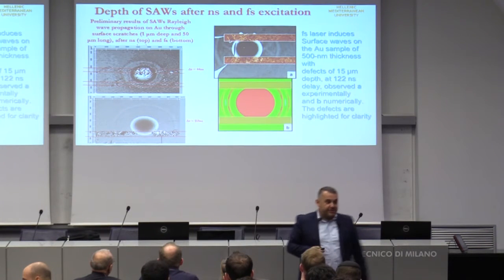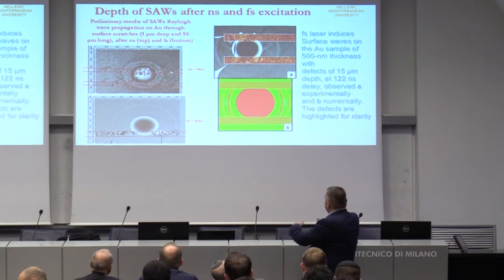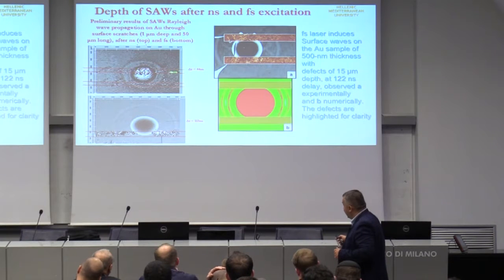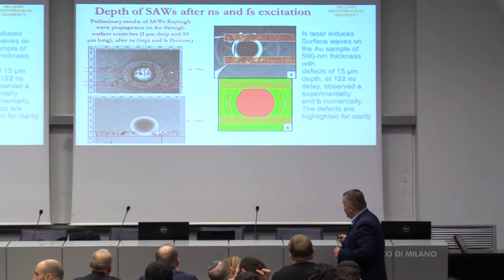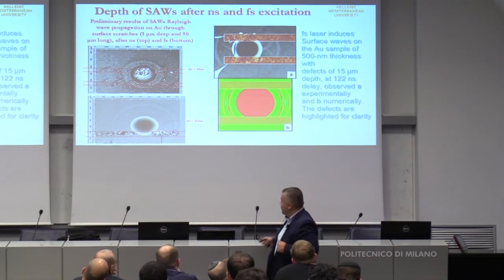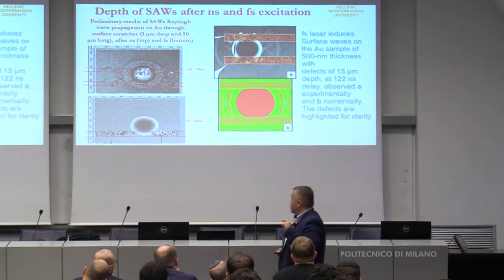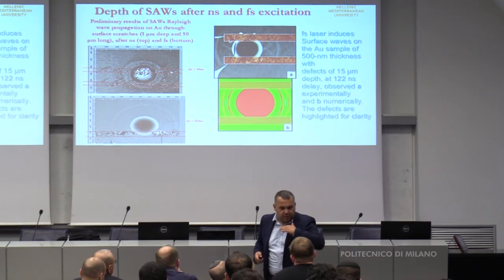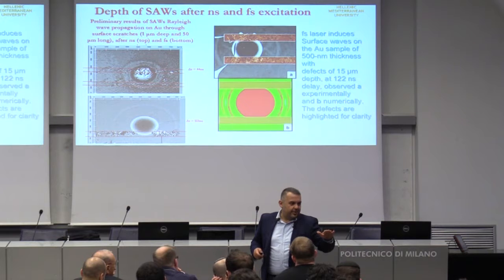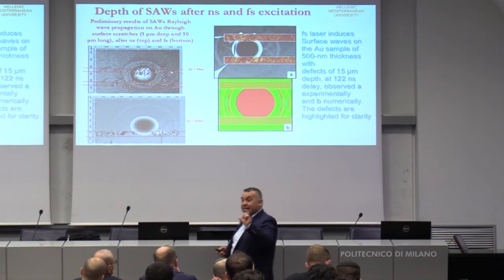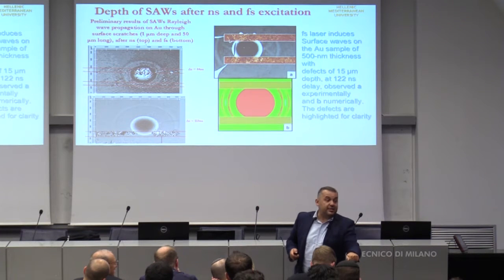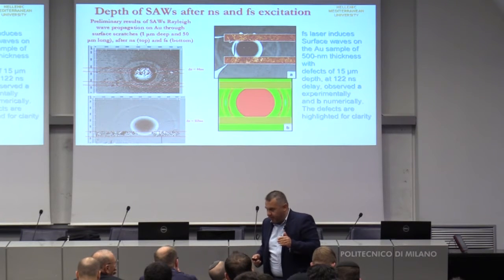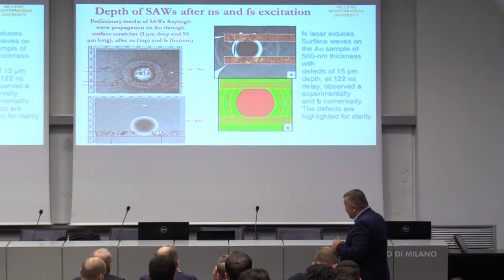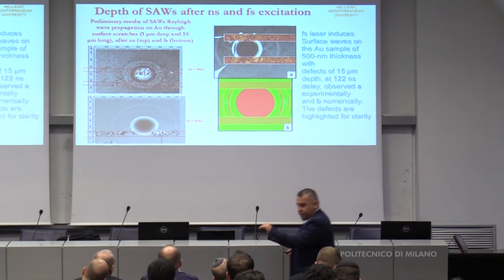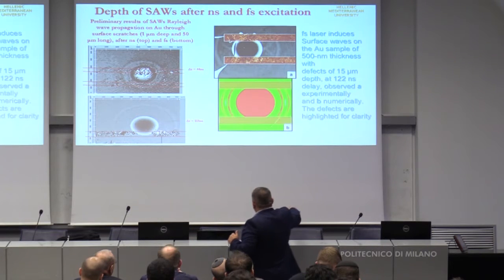The first is for defects. These are experiments of the last 2 months where we are producing some defects here using a laser, and you have seen that if we do nanosecond laser excitation of the surface, the wave propagates past deep defects of the order of microns, 1 micron or more, as if the defect doesn't exist. So the coupling depth of the Rayleigh wave inside the substrate is in the order of a few microns, as we calculated. If we use femtosecond laser excitation, you see here, you barely see the Rayleigh wave, but there is nothing passing through the defect. And this is also proved theoretically.